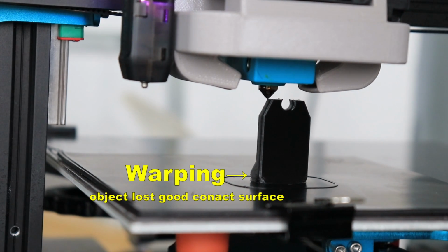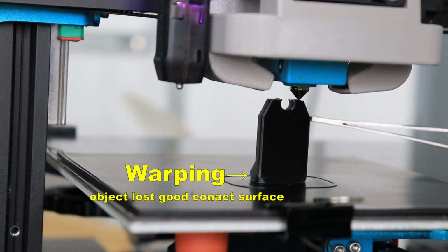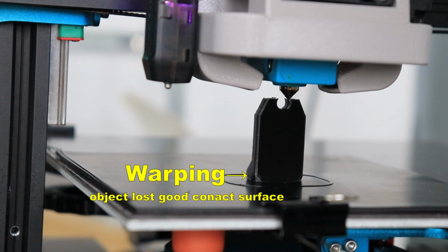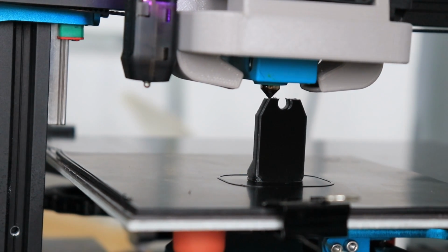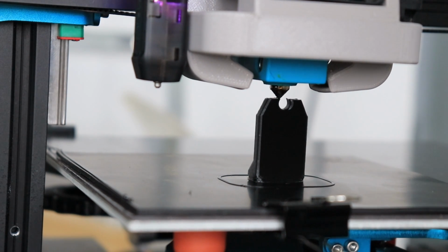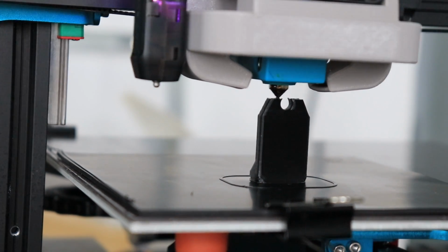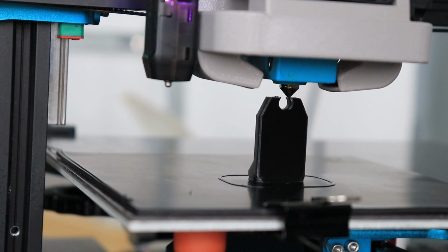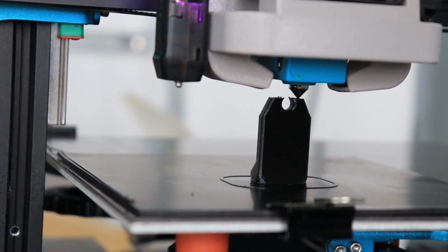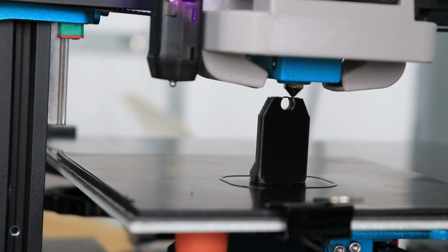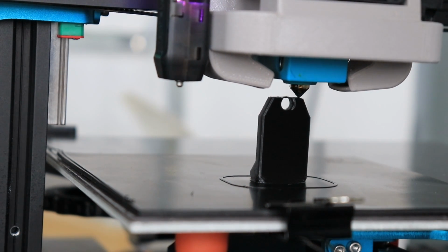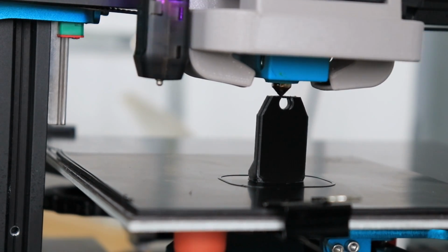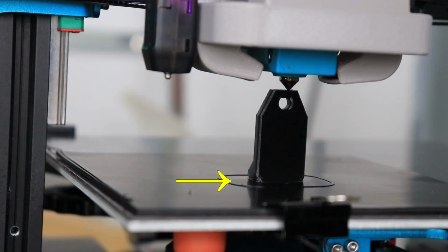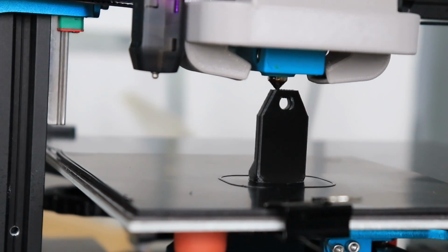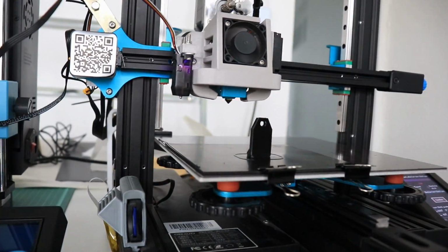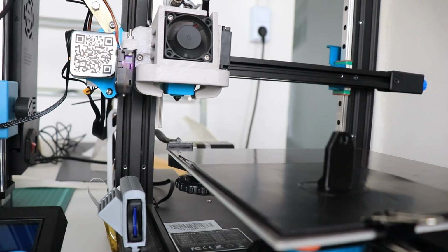Printing is almost finished, but I noticed a wobbling of the object because I can see a little bit of curling up of the filament, and the nozzle touched that material, and I hope it will not break off earlier. The problem is that the plate is not fixed. Only when I saw the bridging, closing of the hole, I knew I could relax and this object would be printed correctly. Only during the video editing I noticed how small that contact surface is, and it was a miracle that printing was finished. This could have had great bed adhesion without that warping.